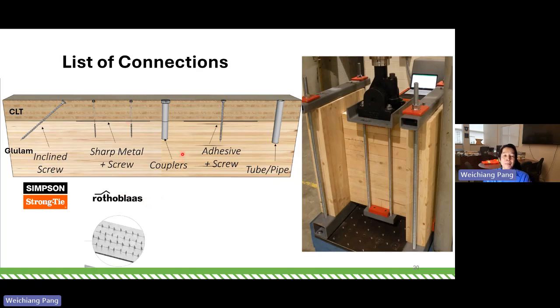We also made our own coupler system with epoxy. You can see the two couplers. This is designed so you can easily take it apart, unbolt it, and take apart the CLT panel and glulam beam. We also tested adhesive with screw. What we use here is the Simpson screw, and then we put the Loctite adhesive in between, to try to give us better initial composite action at the beginning. Usually a screw takes a little bit of slip before it starts to fully engage.